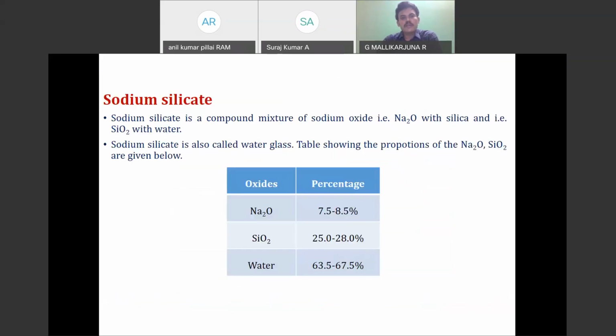And here we have sodium silicate. How are we going to select this sodium silicate solution? In the sodium silicate, the main content is sodium oxide, up to 7.5 to 8%, and the silica varies from 25 to 28%, and the remaining is water content. But we get these directly from the market. The main important thing is that there is no restriction for quality checking, that is, how much content it should have.